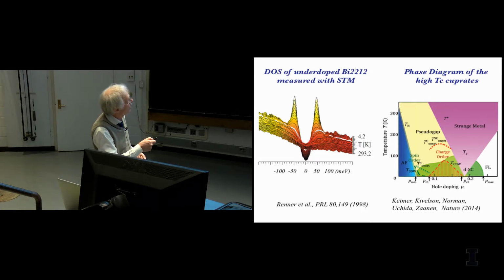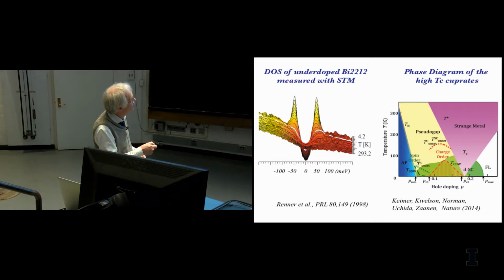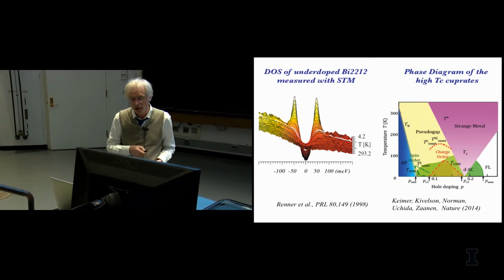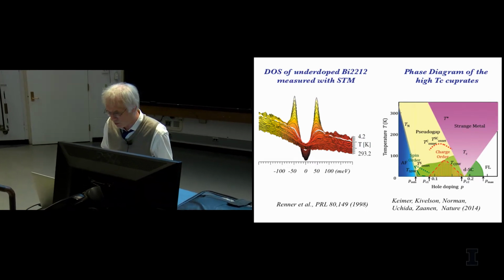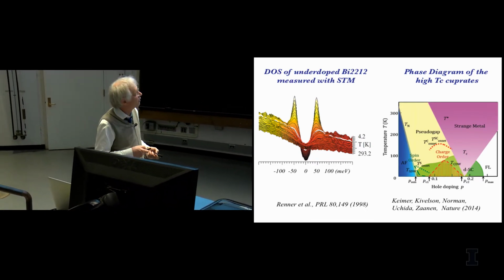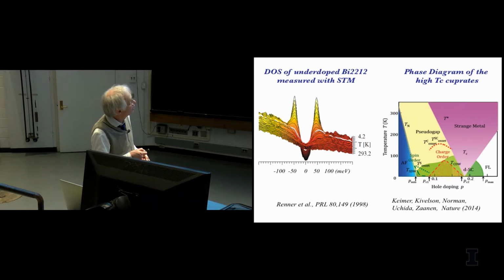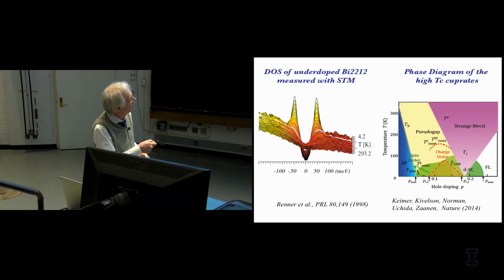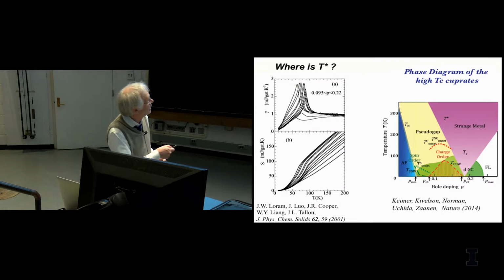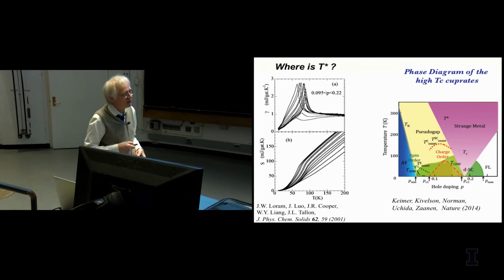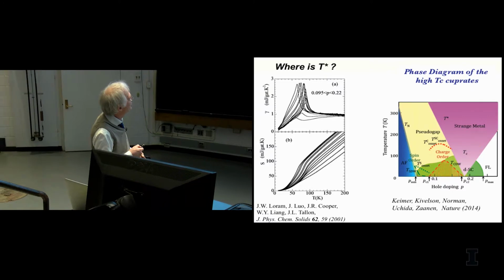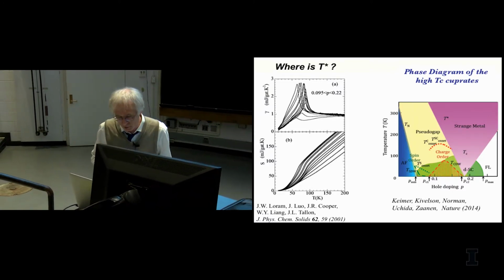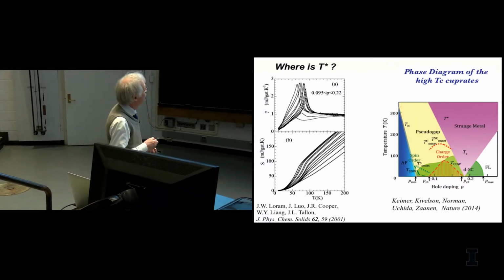And so you're actually coming down around here-ish, and you still see a gap, a very gradual opening of a pseudo gap over here. It's a very clear feature seen in actually all spectroscopic probes, including optics and ARPES and neutrons even. If you go overdoped, they don't show the gap, the gap only opens in the superconducting state. And even for the optimally doped, it's more or less a superconducting state. So here you have this strange metal phase. And there you have a pseudo gap. Now, where is the T star? I mean, where actually does that opening happen? This is something that John Loram, who very sadly passed away half a year ago, made studies of.